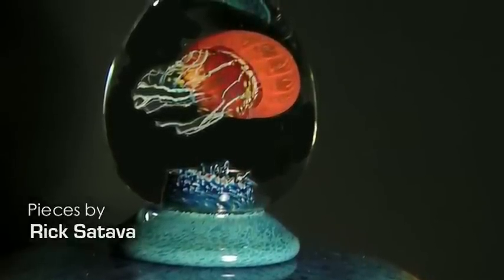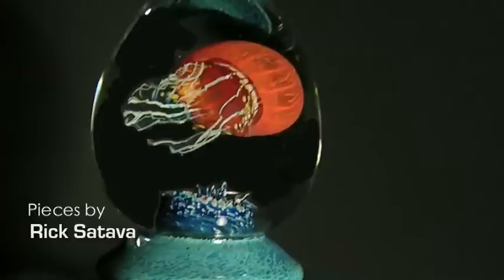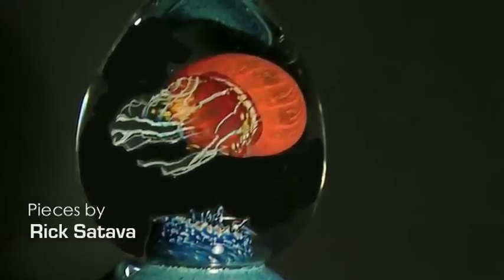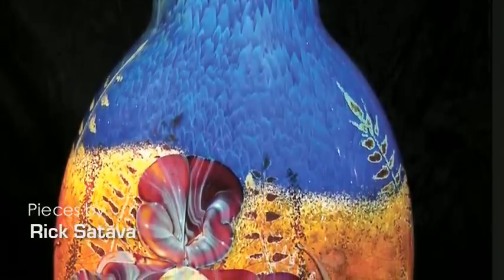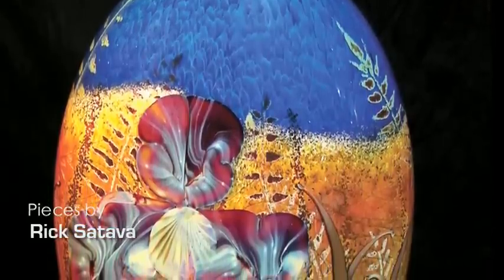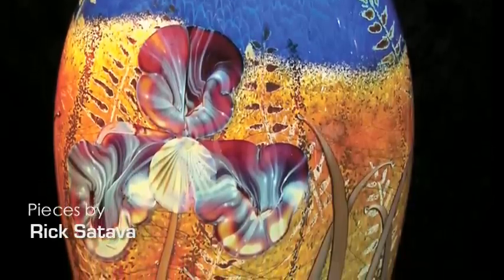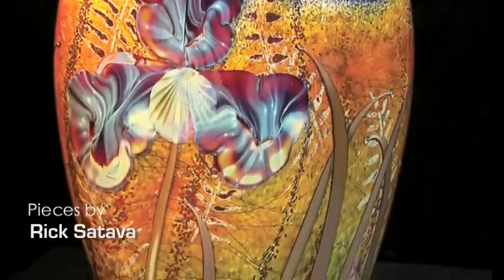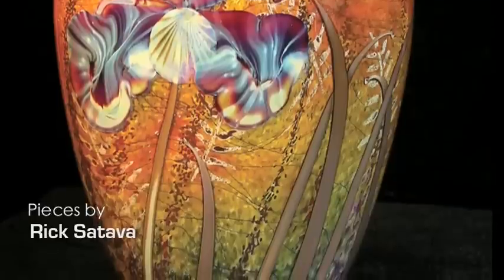Do you use mostly the basics — copper, cobalt, gold — and mix those, or is it more complex than that? Yes and no. I have one furnace that is just for color, and there are five crucibles in there, so I can melt five different colors. I'll take the frit — the drippings from our clear furnace — frit that down, and add whatever I'm adding for that color. For our copper red, there's copper, tin oxide, and carborundum as a reducing agent. We put the reducing agent in the formula since we can't change the atmosphere, because it'll help one glass but affect another.